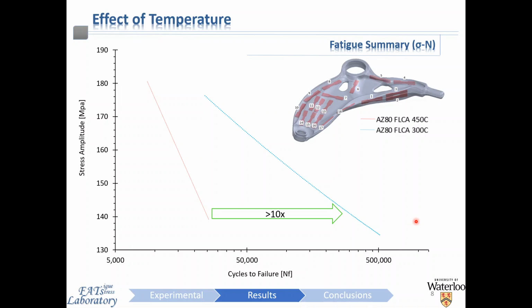So you can simply think of the analogy that the final heat treatment will govern the resulting microstructure, as it does in many materials that we utilize in engineering systems. The precipitate content is also governed by this final heat treatment and the morphology of these precipitates, as well as the final properties. If no specific heat treatment is given, it's the last step of the thermal history during the forging process that effectively is replacing this heat treatment.